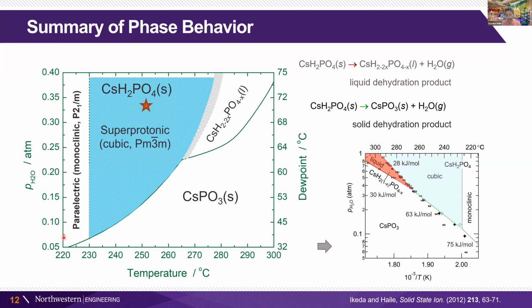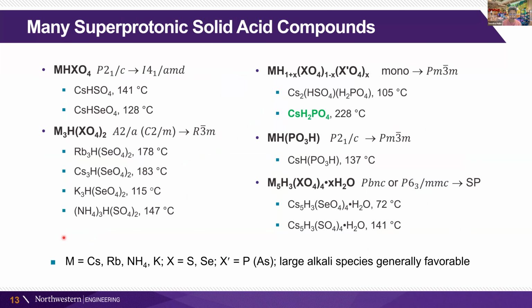So we pass the carrier gas, which is typically synthetic air, through a humidifier that is held at that temperature. This would be the dew point temperature, and again, around 70 to 80 degrees Celsius. It means that the material is a little bit delicate. You have to maintain these conditions to prevent that dehydration, but once you treat it well, it treats you back reasonably well. So there are many superprotonic solid acid compounds that exist.